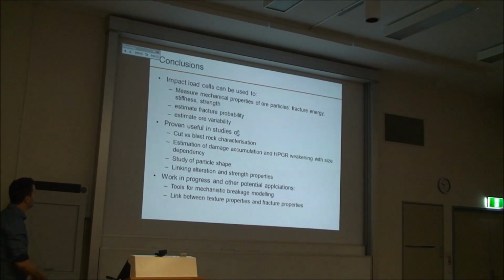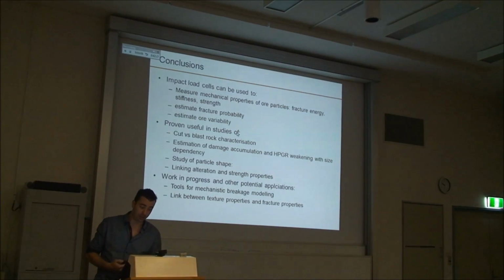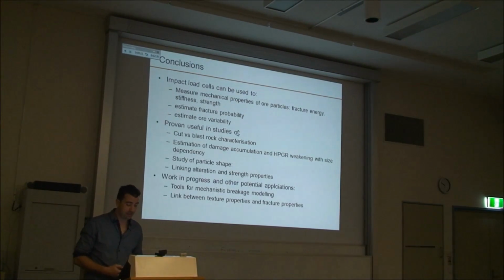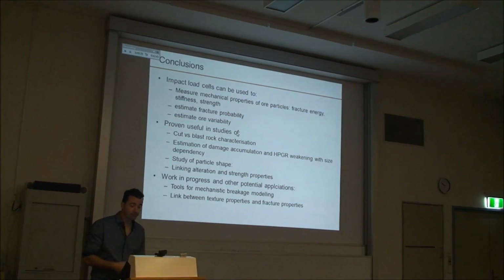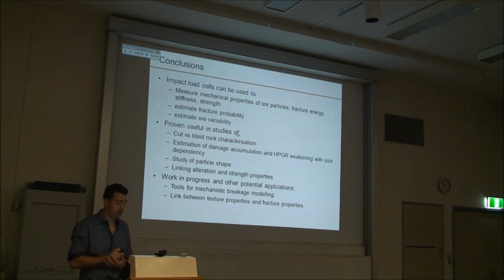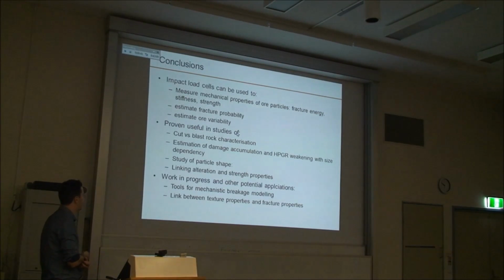So these are the conclusions. We had a look at the impact loads there, what they can be used for. We can measure those mechanical properties. We can estimate fracture probability. We can estimate ore variability by doing this test. And it was proven useful in the different case studies. So the study of the cut and blast, studying the composition and the effect of cutting and blasting, the effect of damage accumulation by HPGR weakening or by repeated impact. We studied the particle shape and the effect on sizing. And then we've seen the useful application of that varies with the alteration index and the strength relationship and the work in progress I just showed.